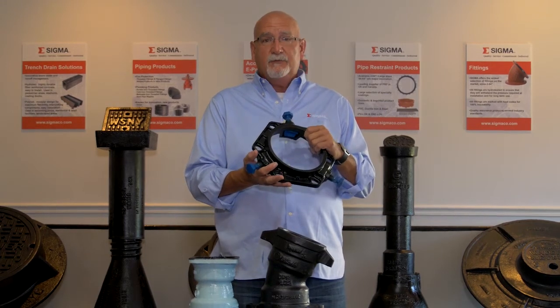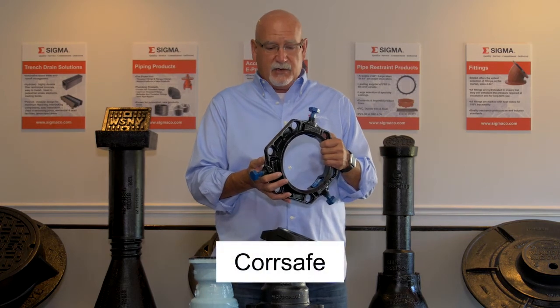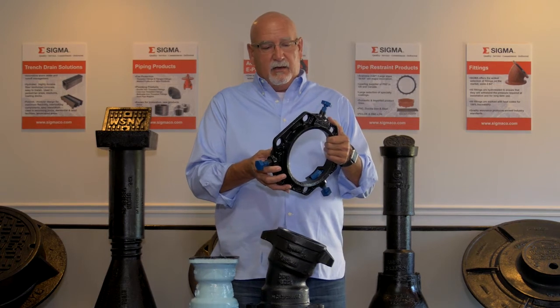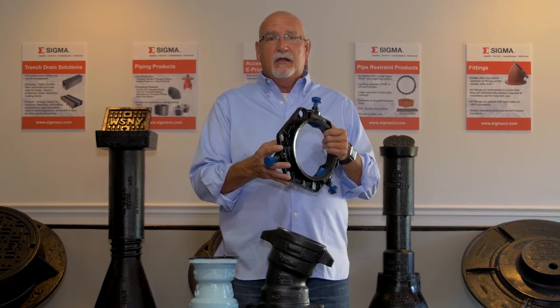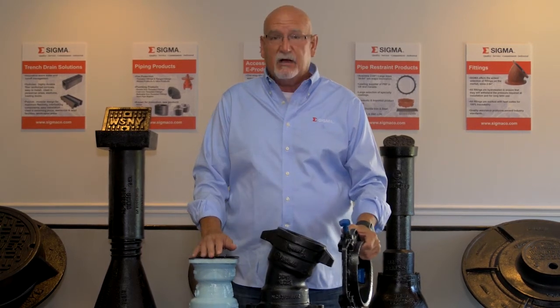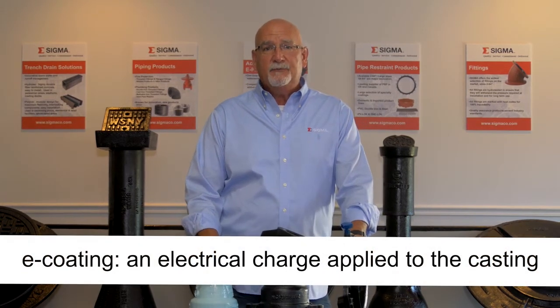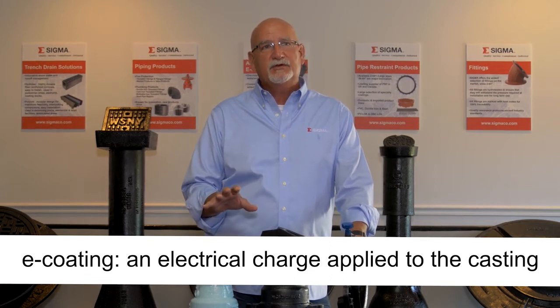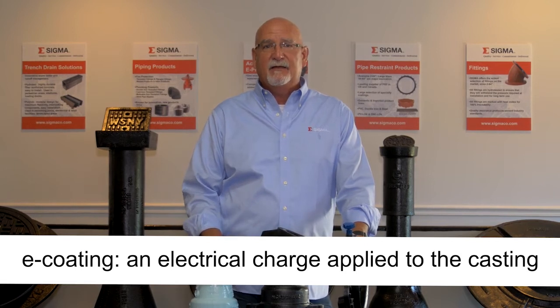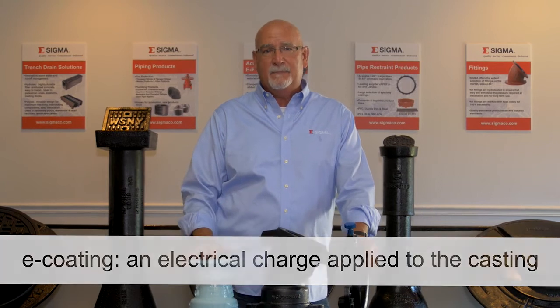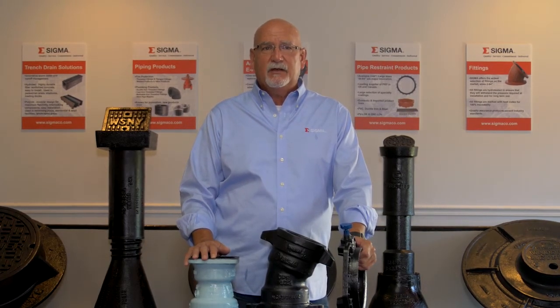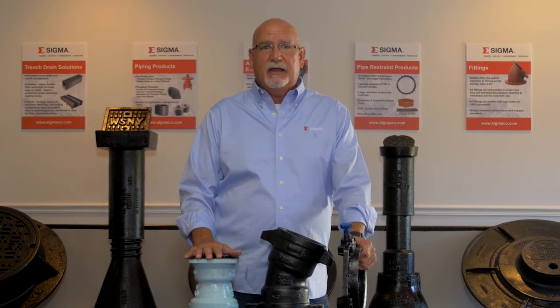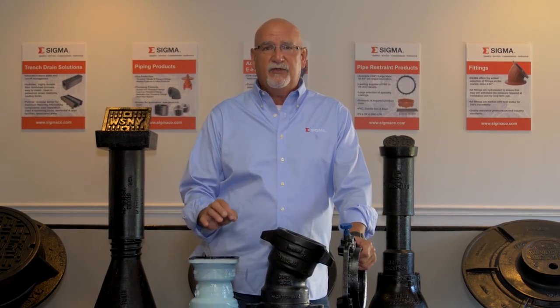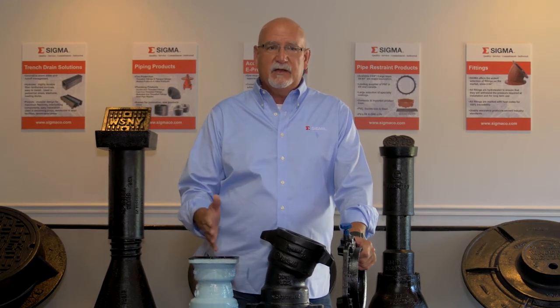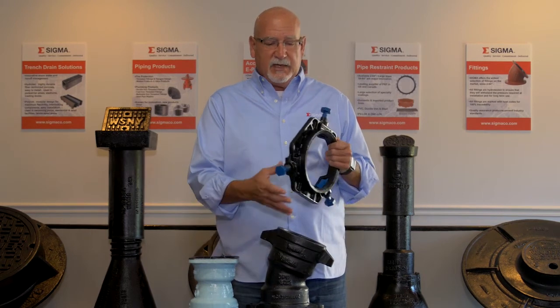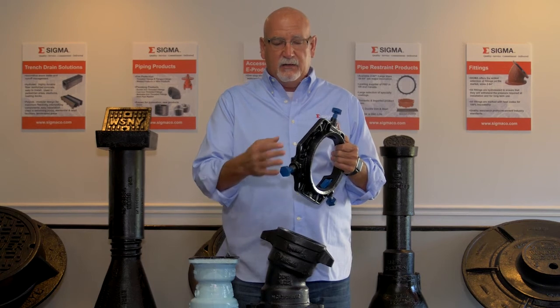So we have a standard coating and a hybrid coating called CoreSafe. The standard coating is an epoxy for all components, and the CoreSafe is another process that we haven't talked about that is also an epoxy process, but it's called E-coating. E-coating is an electrical charge applied to the casting that attracts the solids from a liquid bath of paint. It is widely used in the auto industry. Comes in various colors, but typically the most common is black. And E-coating provides a thin, very controllable thickness epoxy coating that you can then top coat if you choose to, and that's what we do for our CoreSafe. We use E-coating on all the components and then an epoxy top coat.